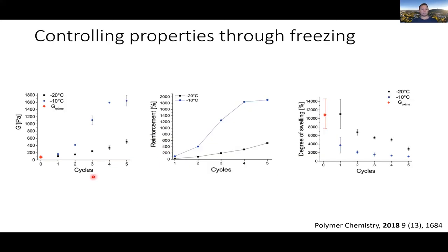And you can see here different cycles of that method of freezing and thawing, we can increase the G prime. So essentially you can think of this as strength. With each cycle, we're increasing the strength of this material. And in particular at minus 10 degrees, we can get really interesting properties here. So we're getting significantly increased strength of these materials by creating these porous structures.